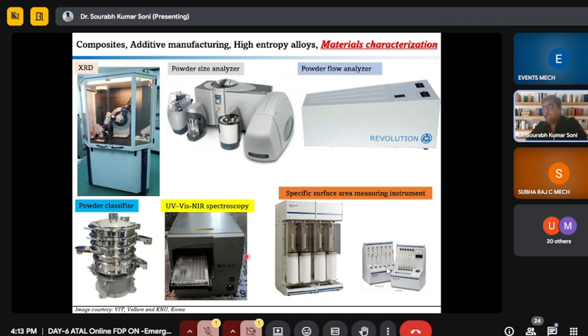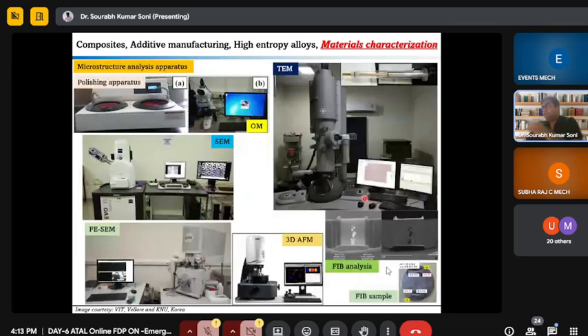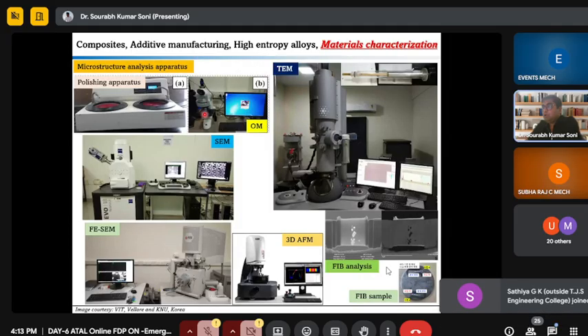This is UV analysis. I use this machine for stability analysis of the dispersed solution. So you can use this also. This is the specific surface area measuring instrument, with which we can measure the specific surface area of the powder. This is the microstructure analysis apparatus, and this one is the optical microscope, followed by the polishing machine. Then we can observe the grain boundary within the prepared specimen.